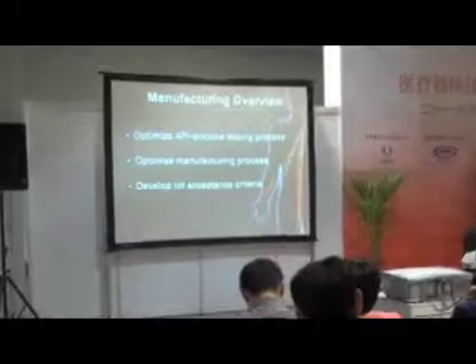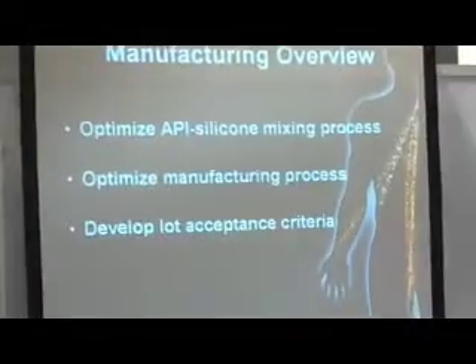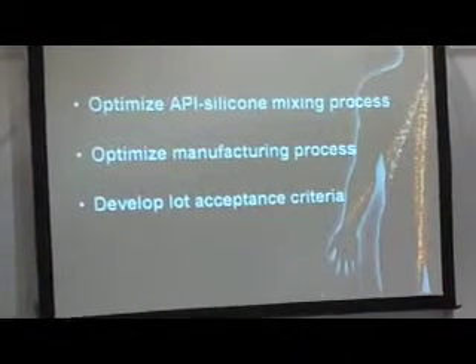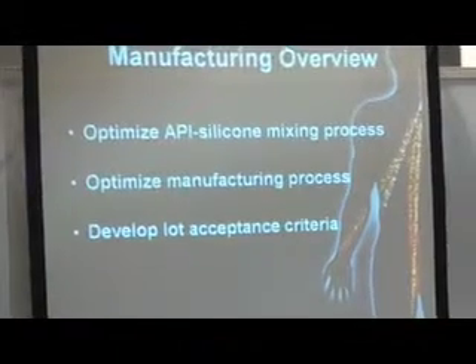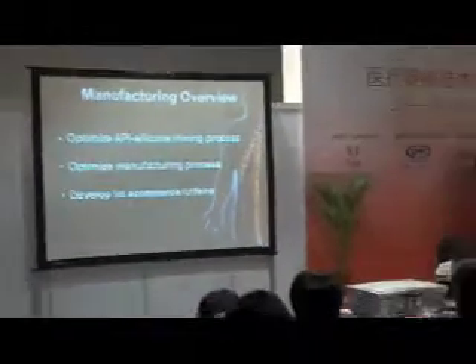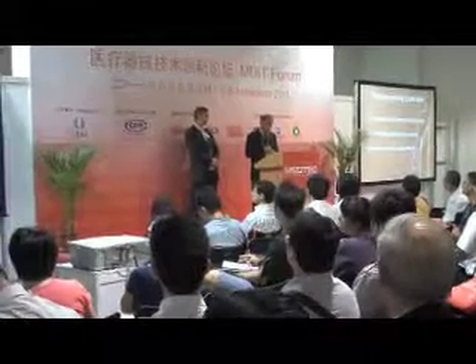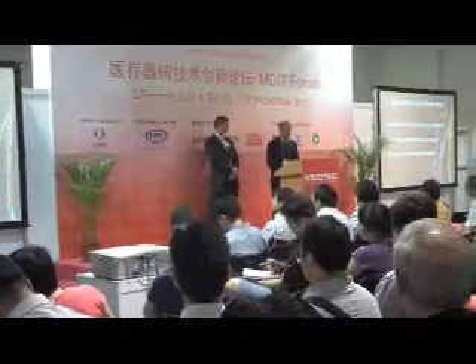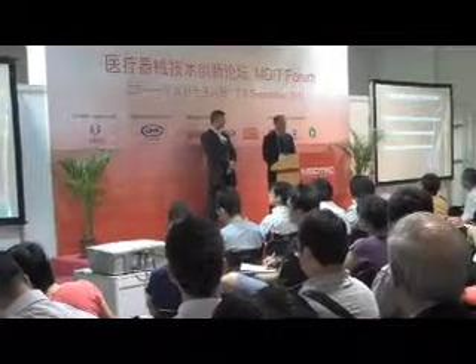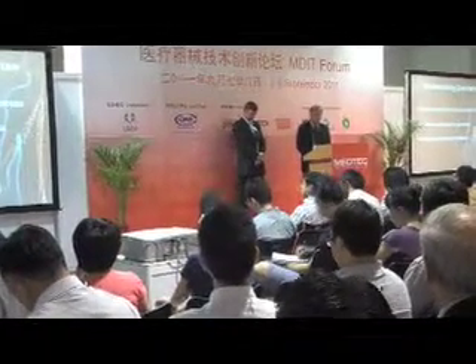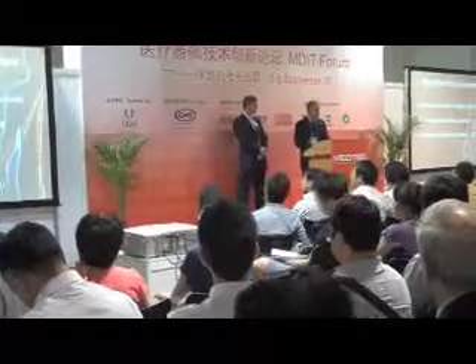I can't emphasize enough how important one element of any process is that concerns a drug and silicone, and that is the mixing technology. In fact, we are only as good as we are competent in mixing and making a silicone drug mixture 100% homogeneous. And our company has in fact invested heavily in mixing technology. We've got mixers that work actually on high frequency sound, which is kind of an interesting technique. We've got other mixers that mix via producing what's called asymmetric dual centrifugal shear forces. So suffice it to say that mixing is important, and choice of mixer is important based on the material.